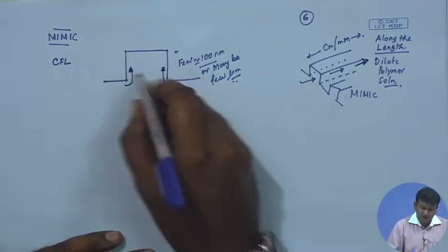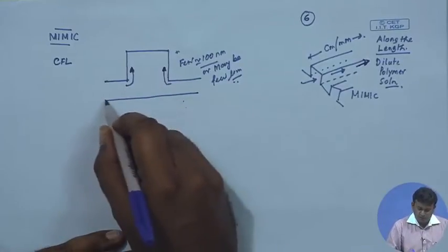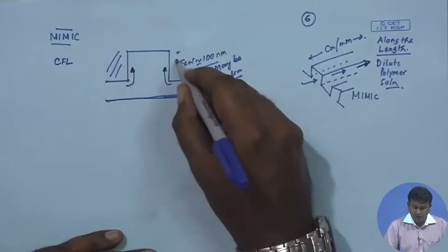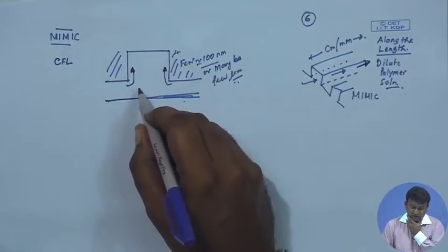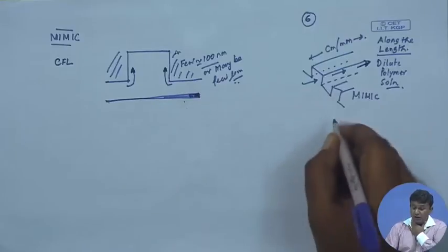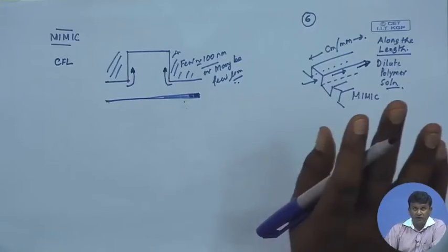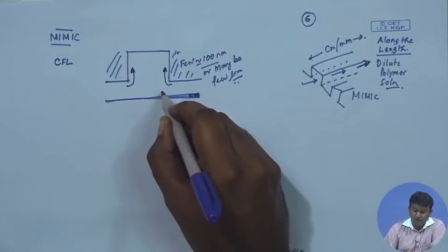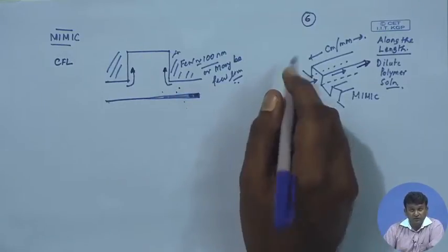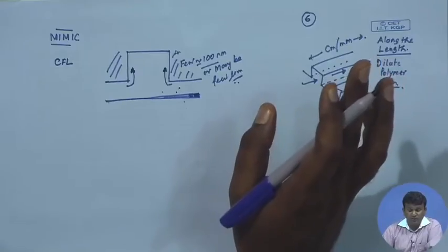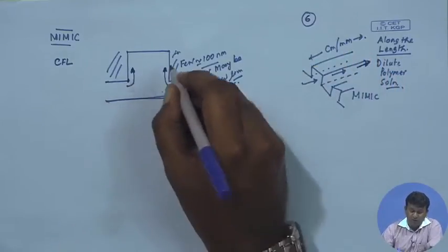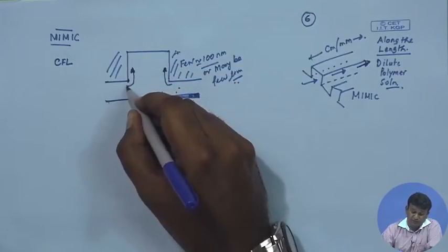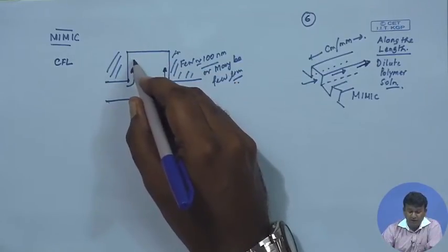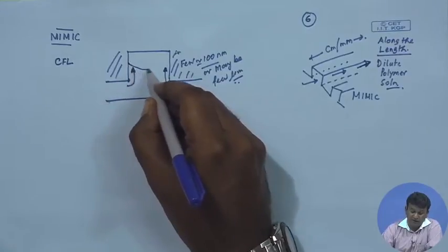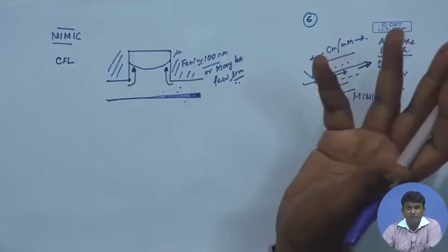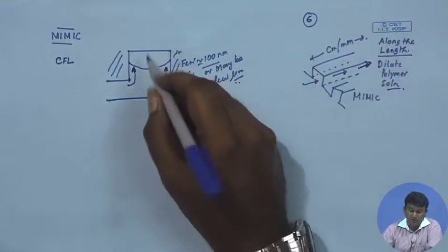Yes, it is quite obvious that if you let the stamp remain in contact with the softened polymer layer, the viscosity is very high, because there is no dilution, unlike MIMIC or SAMIM. You do not bring in any solvent, you just rely on the fact that either you expose this film layer to solvent vapor, or you simply heat it up beyond its glass transition temperature. So, it is a slow process, but the path that the polymer meniscus has to travel is also less. You give some time, you need to optimize it, might be a couple of hours, and you get perfect mold filling.